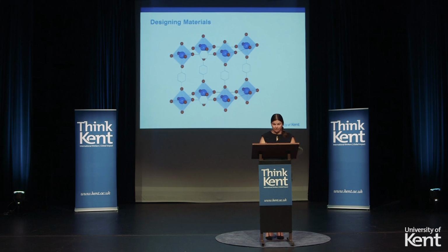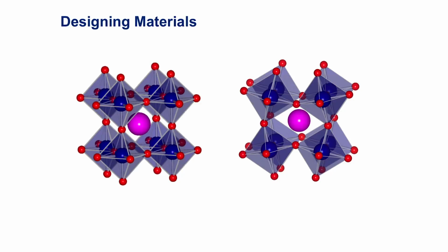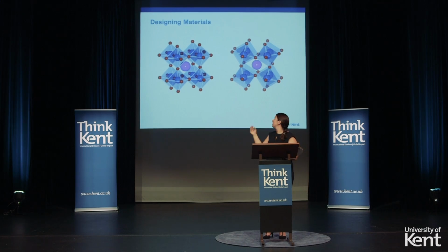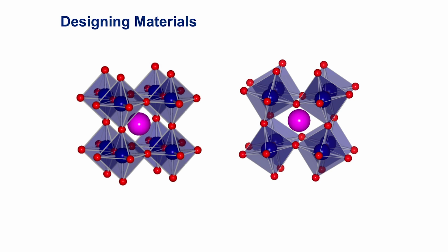We can also change the metal center to be a transition metal with unpaired electrons. This allows us to have magnetic ordering in a material and we start to get magnetic materials. So if we return to our octahedral unit, we can couple it together here through the corners to form what is known as the perovskite structure. This forms a channel in the middle that another ion can sit in, in this case shown by this pink sphere. When the pink sphere and the blue sphere are ideal sizes, we form what is known as a cubic structure. That's a nice regular structure as shown on the left-hand side here.